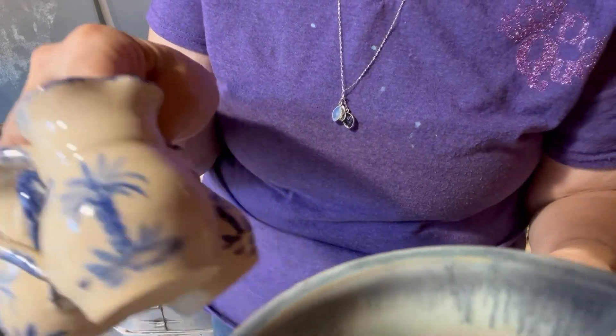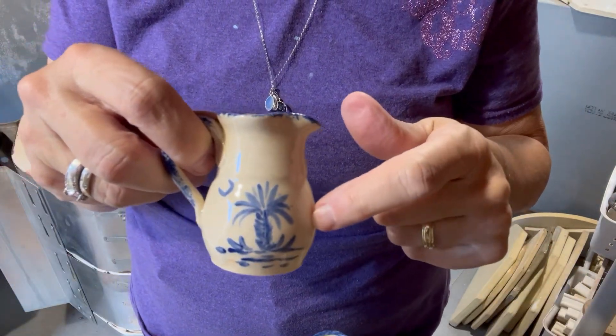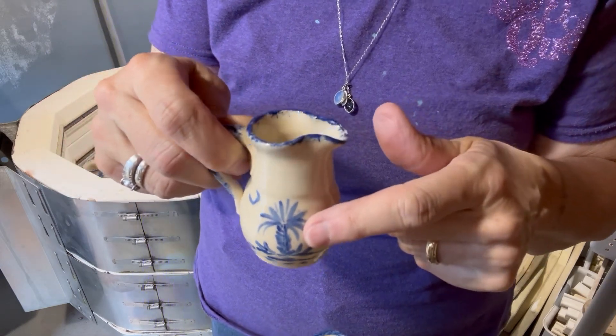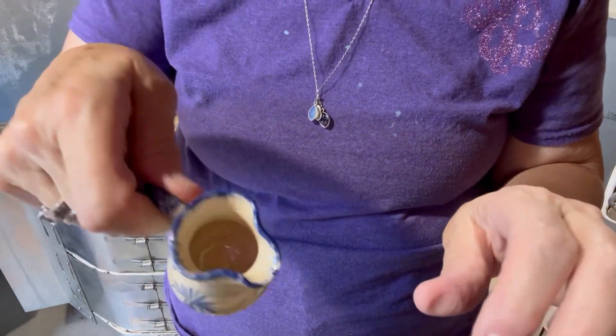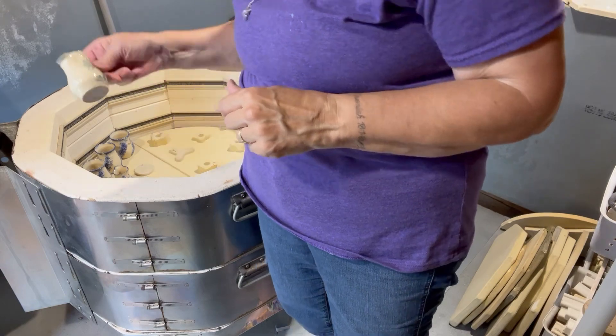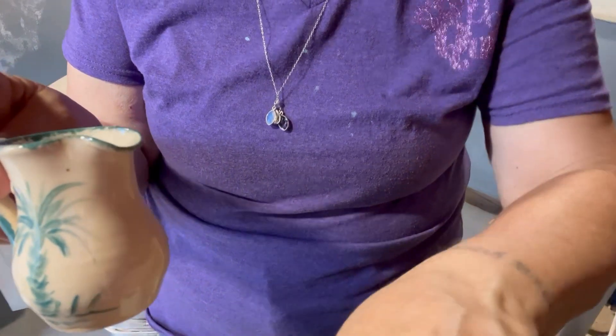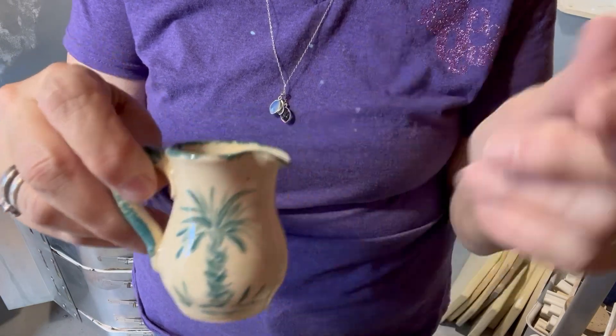These little pieces right here are just my clear glaze. The design is Speedball underglaze, royal blue, and I've sponged around the top just onto the bisque fire, and then I've dumped them into my own recipe of clear glaze. It's a very versatile glaze — it goes from cone four to cone ten. I've done these in different colors. I like the Speedball underglazes; they do well, and my glazes don't run or drip when I coat them with a clear.